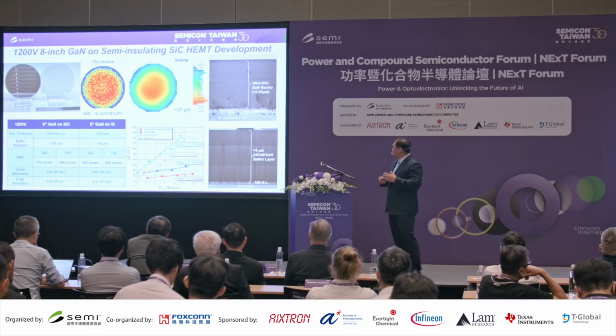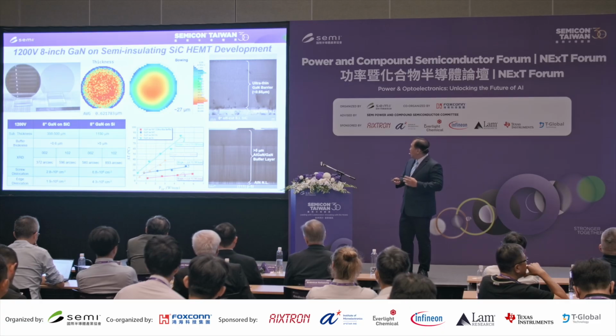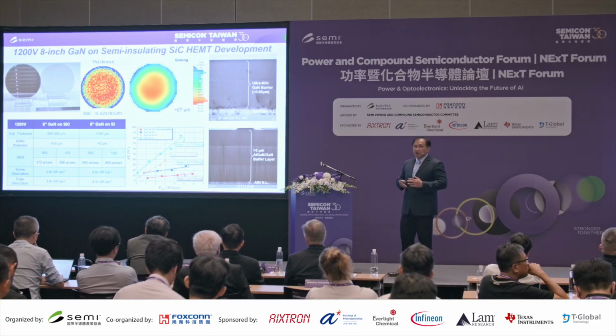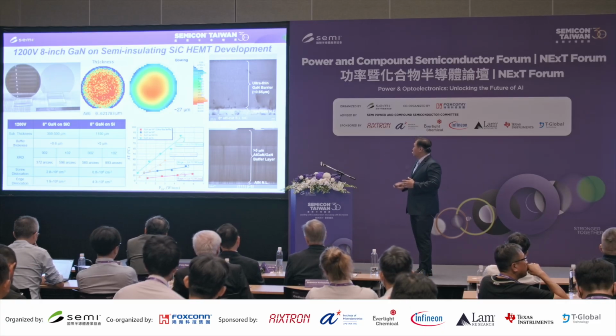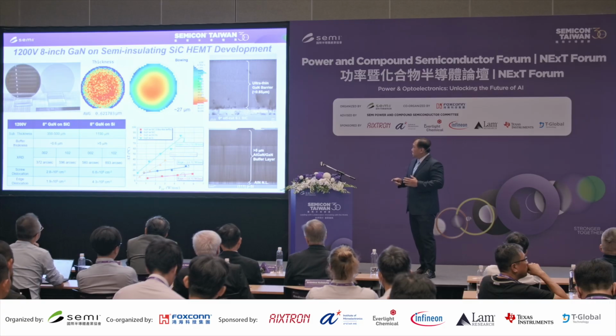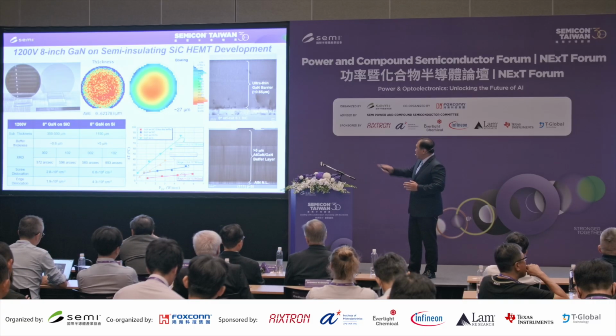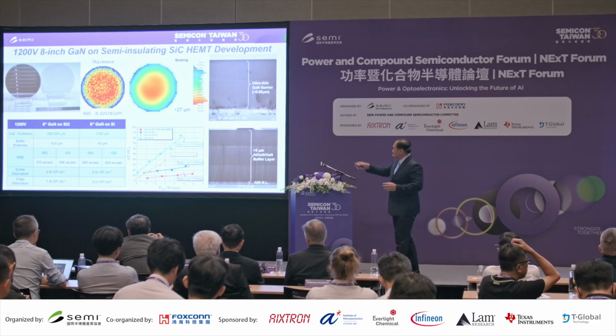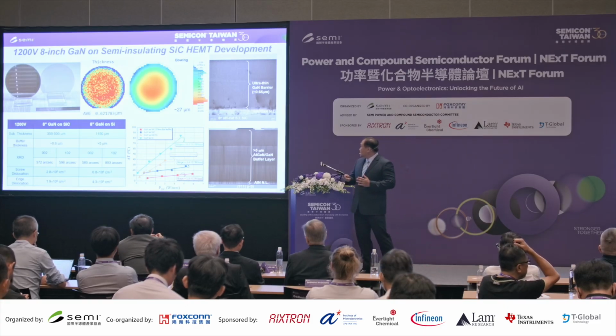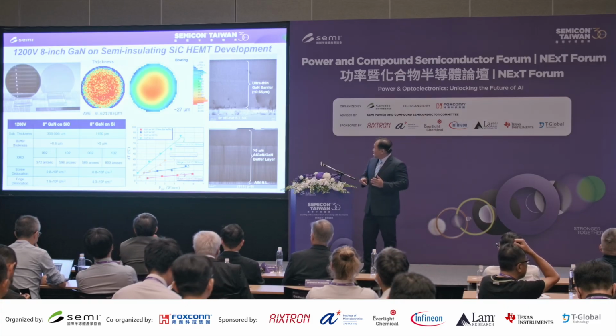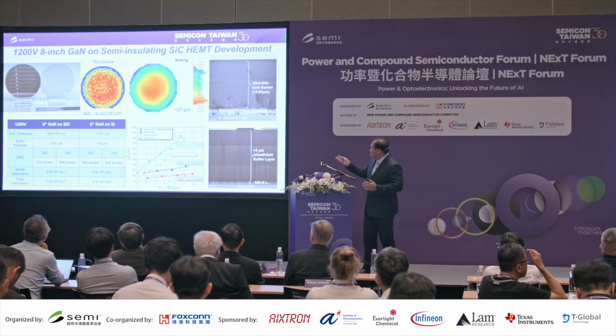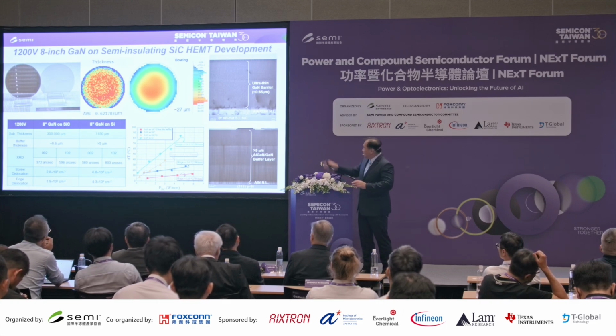So you can just grow a very thin buffer for the gallium nitride epi layer growth. So far we can demonstrate the 8-inch GaN on silicon carbide with ultra thin buffer. And we also measured 4 kinds of device: GaN on silicon, GaN on 3C silicon carbide on silicon, GaN on silicon carbide 1.5 micron, and GaN on silicon carbide ultra thin barrier. Okay, there are 2 groups.